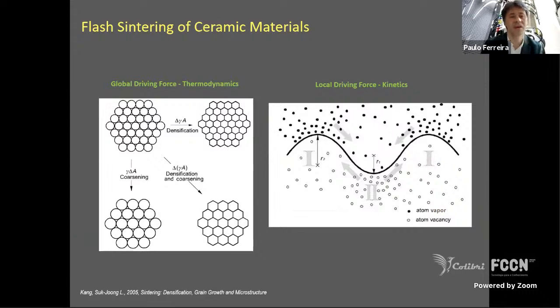Just to finish up, another example about flash sintering. The idea is to sinter ceramic materials. This is basically through densification and coarsening. And the local driving force is kinetic. In other words, the curvature: you have positive curvature and negative curvature. So there is a difference in chemical potential between the top and the bottom. And this leads to a flux of atoms, where the atoms move from the top to down and the vacancies from the valley to the top.